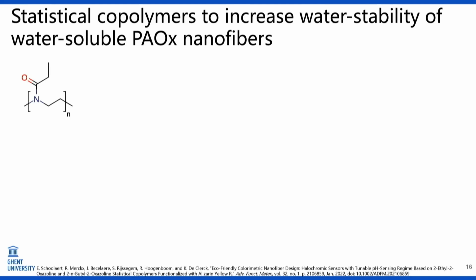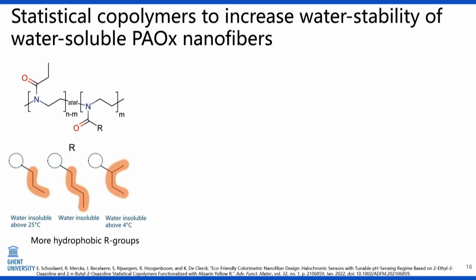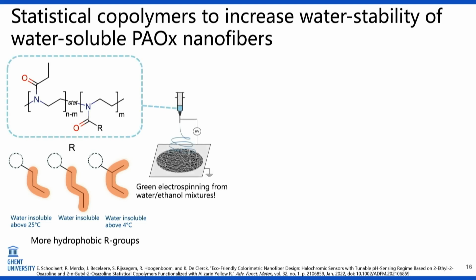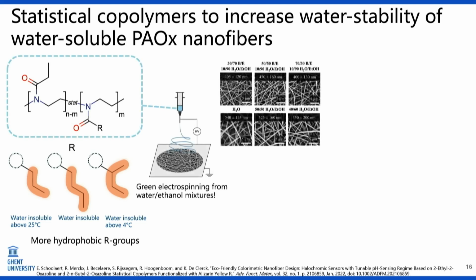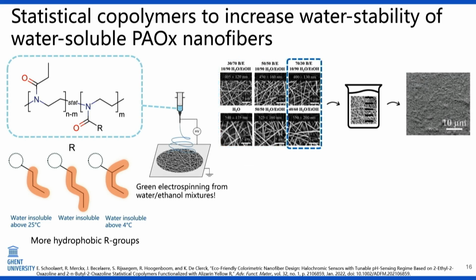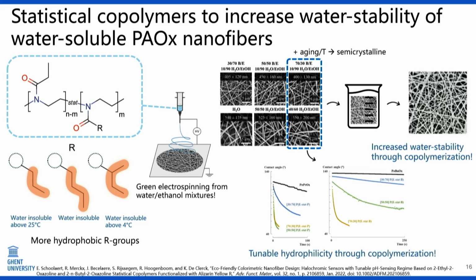And then the last strategy that we used to introduce water stability was using statistical copolymers, introducing here the ethyl oxazoline combined with a more hydrophobic oxazoline. We used both propyl and butyl oxazolines, and we could spin them from aqueous solutions again. Depending on the ratio, we could either retain the water solubility or make them water stable without having to do another post-treatment. And in addition, of course, depending on that ratio, these statistical copolymers are ideal to tune the hydrophilicity.